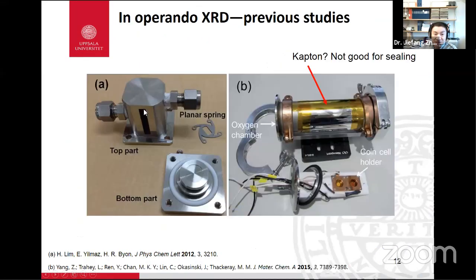Here, for example, this uses a normal in-house XRD. The X-ray beam comes in from this side, passes through the sample, and gets out from the other side. So this is the transmission mode. This example uses Kapton as sealing, but Kapton is not good for sealing for a long time. It can only sustain for a couple of hours.